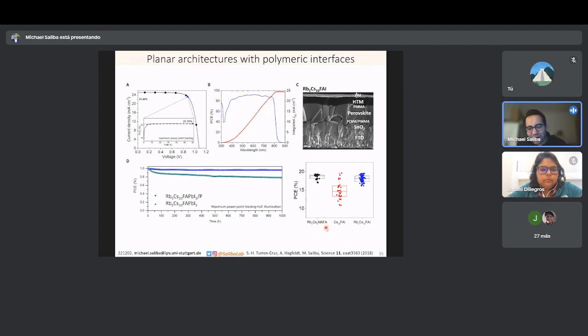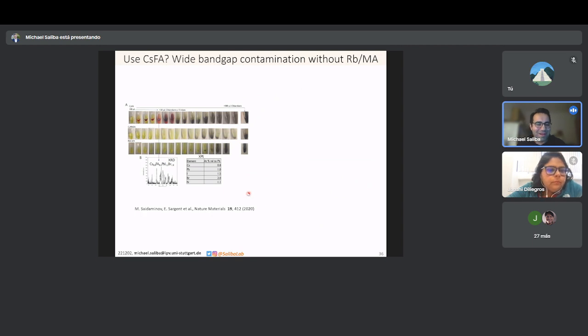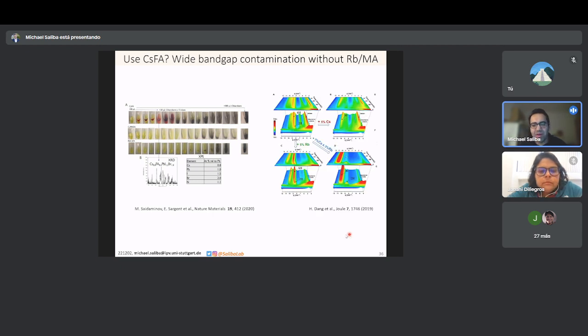And why is that? So there was a follow-up work by Saidaminov and Sargent in 2020, and they showed in the precursor that the double cation perovskite cesium FA, upon exposure to chloroform, that's an antisolvent, forms wide band gap contaminants, whereas the triple cation, both in its cesium MA and in its rubidium cesium version, they don't have this wide band gap contamination. So the hypothesis is, why is cesium FA less reproducible? Because it forms tiny bits of wide band gap materials during the formation process. And that's what, in the end, harms you when the perovskite is formed. That's something that also Aram Amassian in 2019 showed, that rubidium was necessary to form the black phase with as little yellow phase impurities as possible.